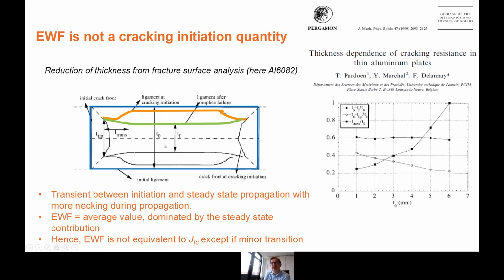But the point I want to make here is that at initiation, the thickness, I will call it T-tip, and T-tip is not equal to TF. And you see the green profile shows that there is a continuous reduction of the thickness over a length which is a transient length. The exact values are given on the right graph as the open circles. And by the way, there are different starting thicknesses for that material.